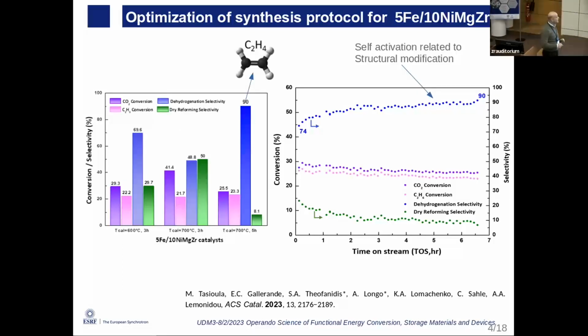Okay, so the conversion increases from 70% to 90% as a function of time. And in the same graph, we see the conversion is basically around 21%. That is quite interesting as well, from a physical point of view. So this means that self-activation is occurring, and this is definitely related to the structural modification that can occur during the reaction. So then we wanted to understand why and how this can be helpful to refine that catalyst in the future.